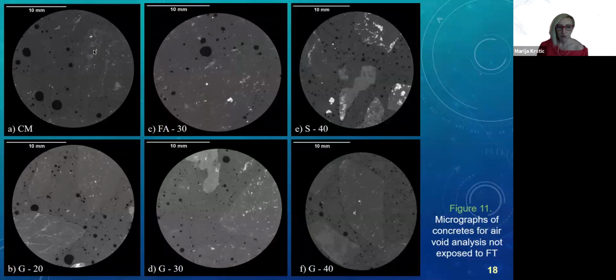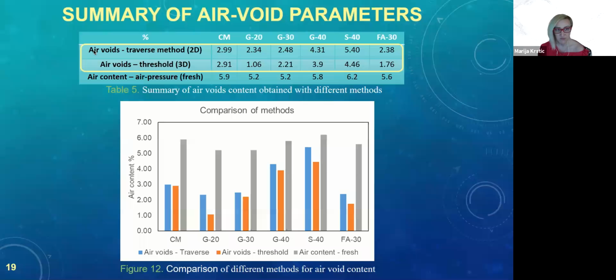These are the micrographs from the beam samples that were not exposed to freeze-thaw, and they were used for air void analysis. Here is the summary showing the air content of fresh concrete when we were making concrete, and it was about 6% or so. And then here highlighted is the air void content by the traverse method, or 2D approach, and by thresholding. And we can see that results are very comparable. The traverse method might be a little overestimated because some of the voids could be a little larger than 1 millimeter, but I would say thresholding might be more appropriate.